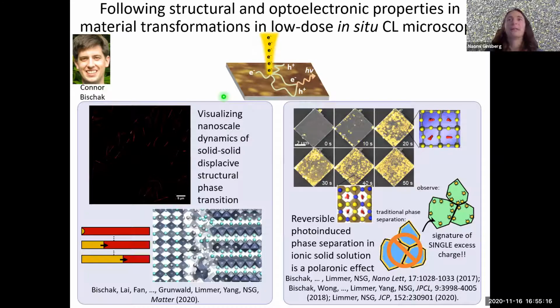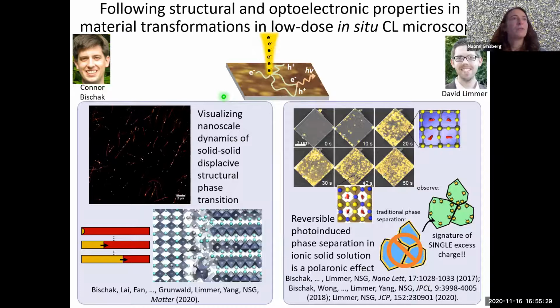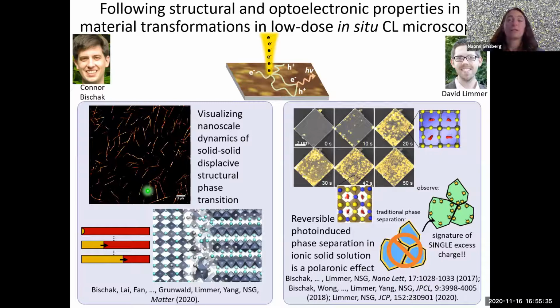So determining mechanisms of two different phase transitions in these halide perovskite semiconductors, especially in collaboration with my colleagues David Limmer and Peidong Yang. Okay, so here's one example where Connor imaged a thermally induced structural transition to the perovskite phase from another structure in these rods that's so different that the halide ions have to actually diffuse through a liquid-like interface for it to happen. So this is definitely like a multi-step process, but it's one that we can quantitate.